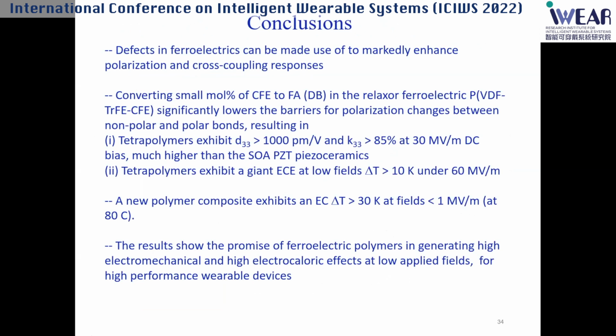I gave you an example in the polymers, where you just convert 1 or 2 mole percent of CFE into the FA. In this polymer, PVDF-TrFE-CFE, we could generate piezoelectric constant and electromechanical coupling much higher than in PZT. These materials also give you a very large temperature change at 60 megavolts per meter, a voltage you can use reliably in a device.